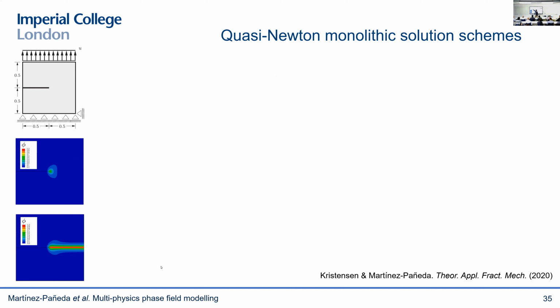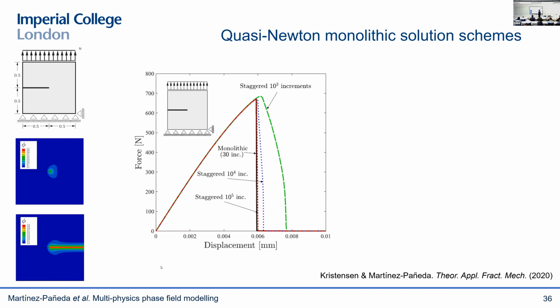So this is a classic benchmark in the phase field community. We have a square plate with a crack. This is a linear elastic solid, so the crack will propagate in an unstable fashion, mode 1 fracture. And this is the kind of force displacement result that you get. So you go all the way up, and then suddenly you get this sudden unstable crack growth event. So you lose all the load carrying capacity. And you can see that the monolithic approach is able to give you the right result with only 30 increments.